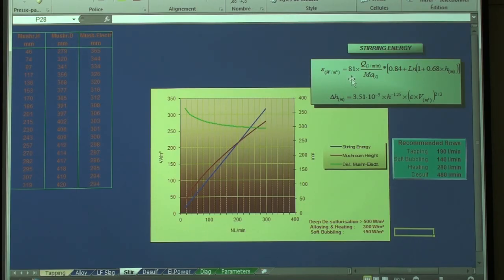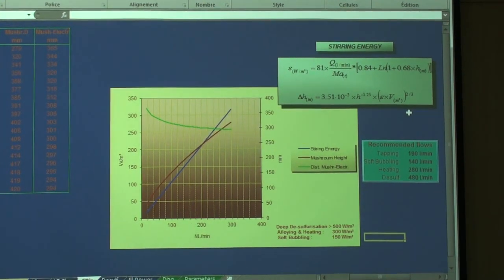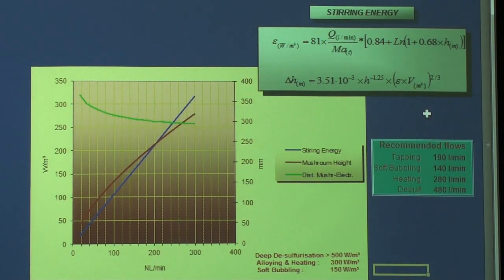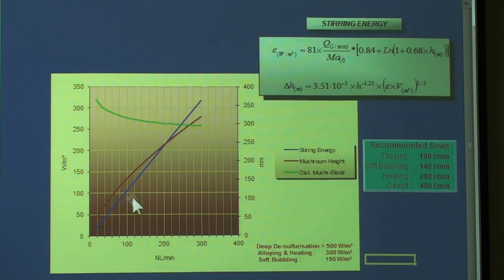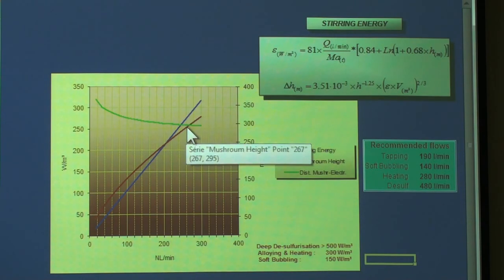And the watt per cubic meter are calculated according to this formula, where Q is the flow rate, MA is the ladle capacity in tons, and H is the height of liquid steel in the ladle. Underneath, this is the mushroom height. When you stir, you make a mushroom, and this is evaluating the height of the mushroom. So, where H is the metal height, epsilon is the energy of stirring, and V is the flow rate. So the blue line is the stirring energy, the red line is the mushroom height, and the green line is the distance between the mushroom and the electrode.